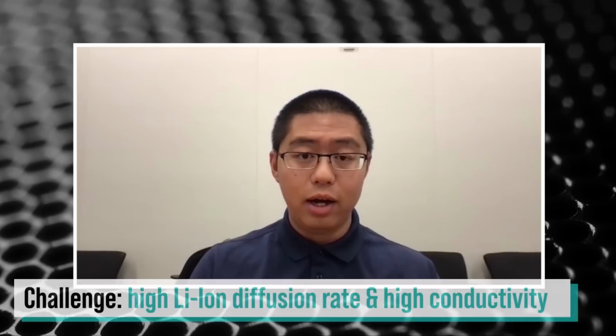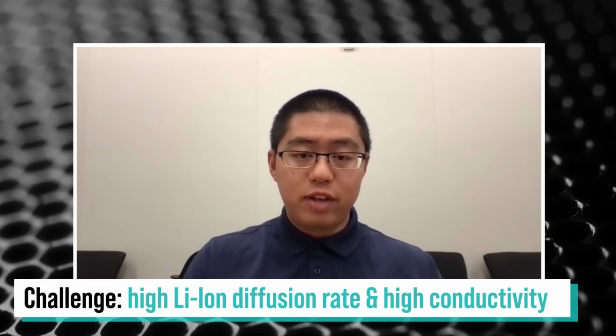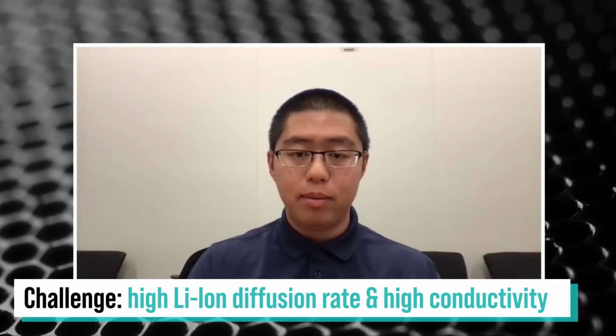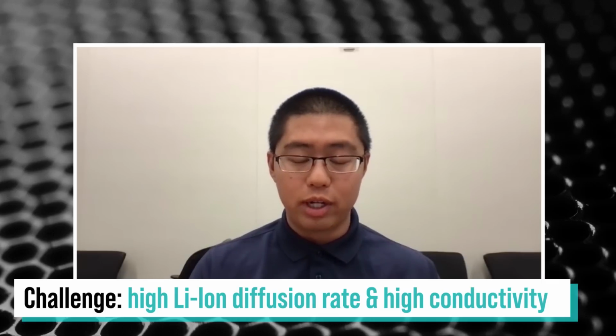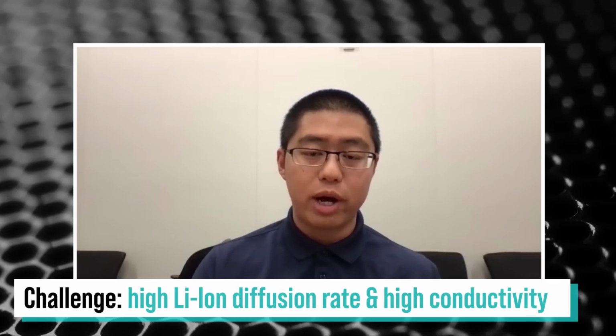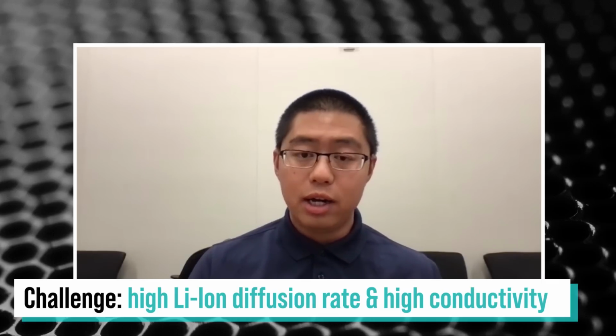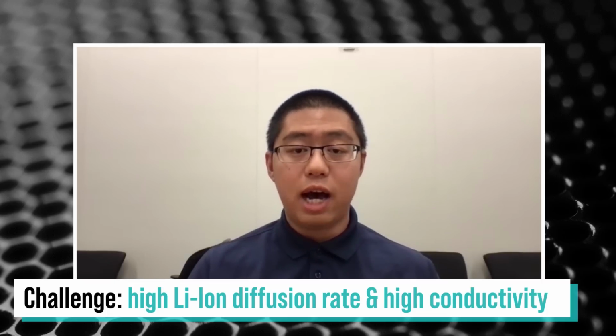Yes, for example, the synthesis. The synthesis is still challenging in getting high lithium-ion diffusivity and high electrical conductivity at the same time. That's why we developed the ionothermal synthesis process, but this one is also not well established. We are just making progress. So that's our first challenge.